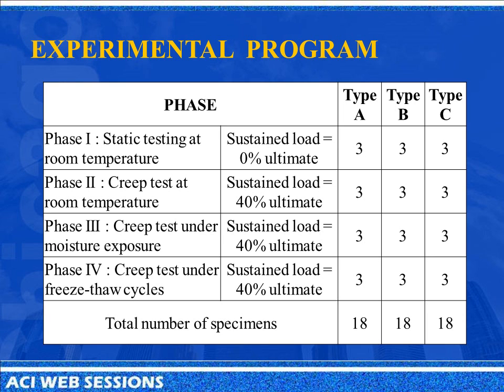This table summarizes the experimental program that we took. It's basically divided into four phases. Phase one was the static pullout testing under room temperature, just to develop a baseline. Phase two is long sustained load creep testing under room temperature. Phase three was creep testing under moisture exposure, and phase four was creep testing under freeze-thaw cycling. We used three types of commonly used adhesives, and the load level for all the creep testing was 40% of the anchor yield strength, which was about 32 kilonewtons.